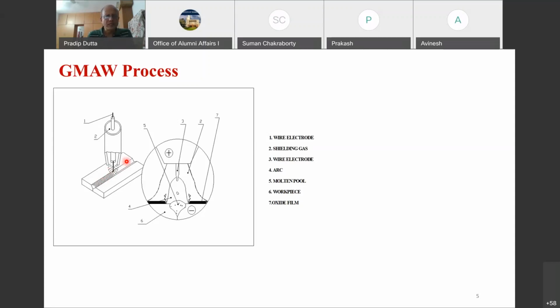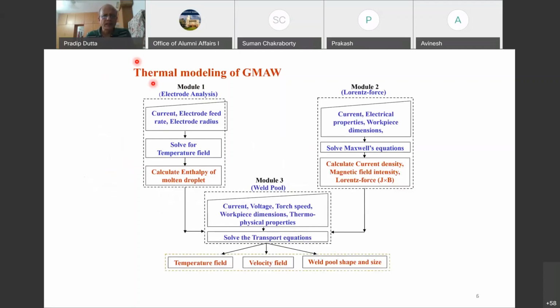So, but this process again is very complex and has a number of phenomena. So that's why our approach was to divide the process into various modules. One module would be the electrode analysis, which would ultimately calculate the enthalpy of the molten droplets which would come in. Another module is to calculate the electromagnetic force which would affect the weld pool convection, and it would calculate the current density and finally the Lorentz force. And both these would be combined to do the weld pool modeling, which would have inputs such as current, voltage, torch speed, work piece dimension, etc., along with the thermophysical properties. And we solve the transport equations to get the temperature field, velocity field, weld pool shape and size. Again, this is one of our earlier works. It was published in the early 2000s.